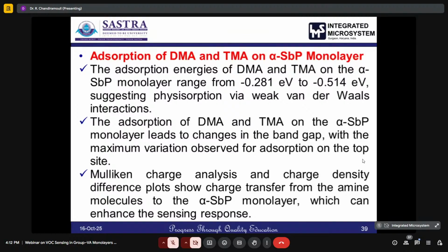The adsorption energy of DMA and TMA is calculated, and it is in the range of minus 0.281 electron volt to minus 0.514 electron volt. It indicates physisorption due to weak van der Waals type interaction, so the target molecules can also be easily desorbed. The adsorption of DMA and TMA on the alpha SbP monolayer leads to changes in the band gap, with the maximum variation observed for adsorption on the top site. Atomistically we can also find which site is feasible for adsorption. Mulliken charge analysis and charge density difference plots are also calculated, and the sensing response is also found.